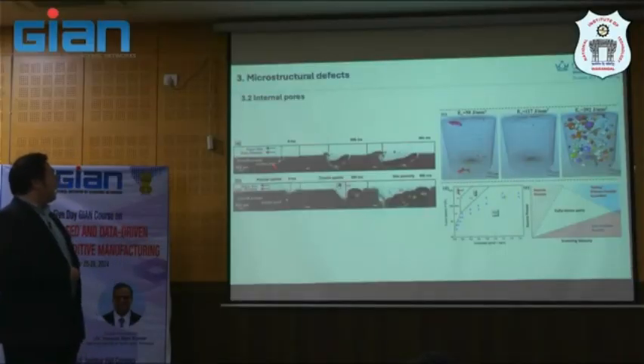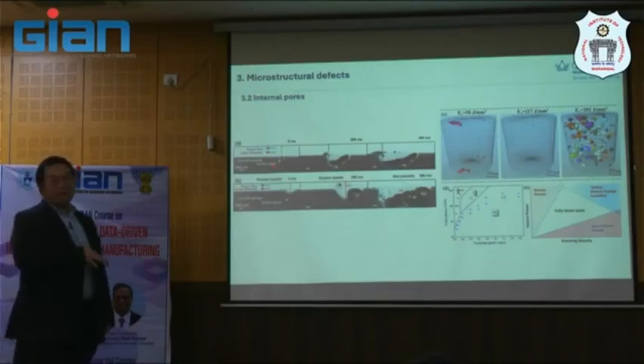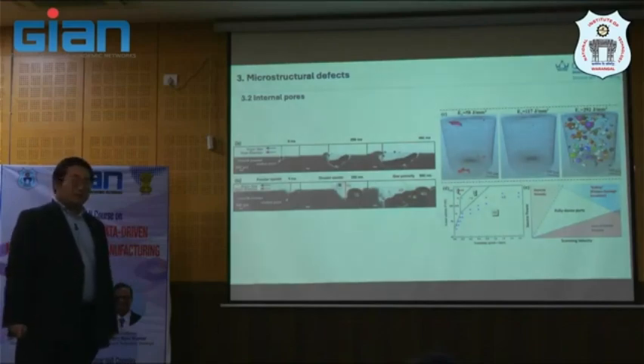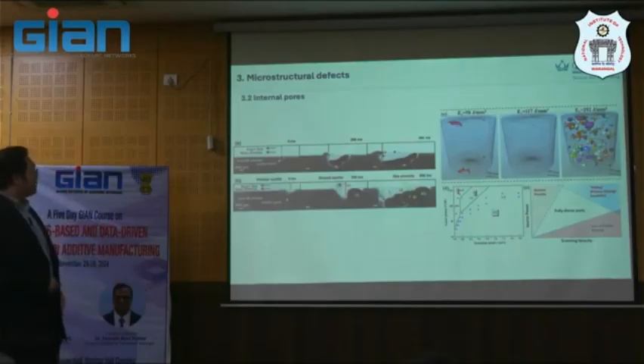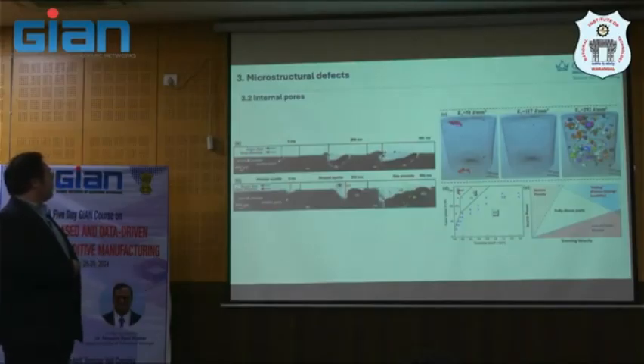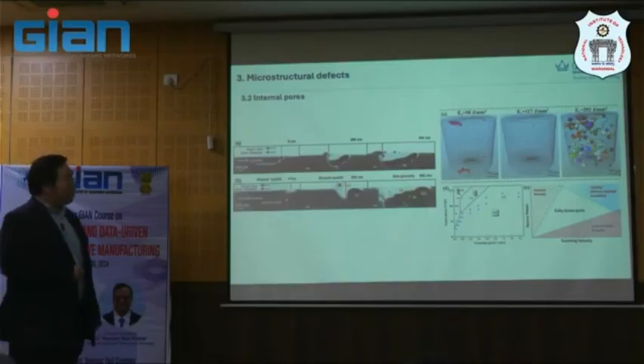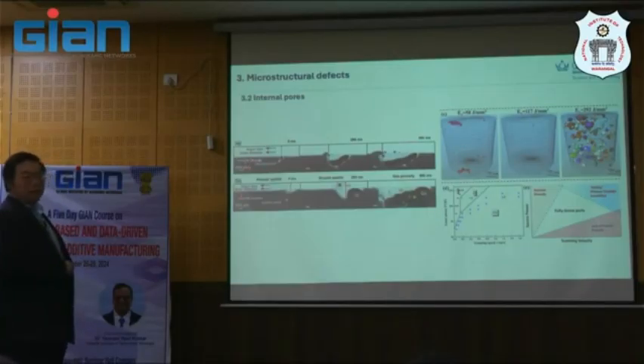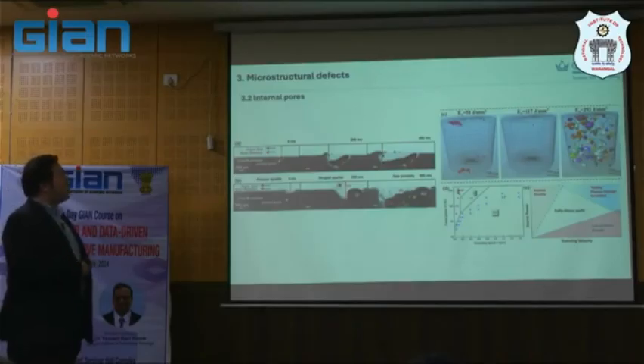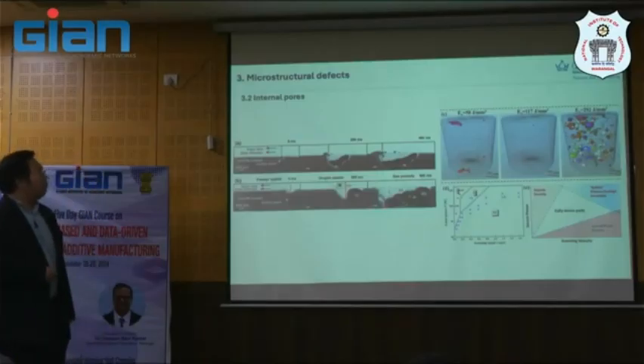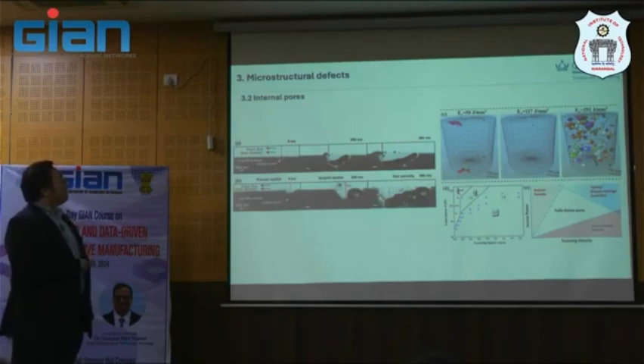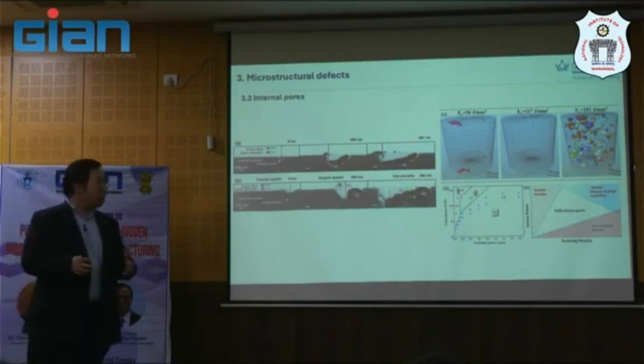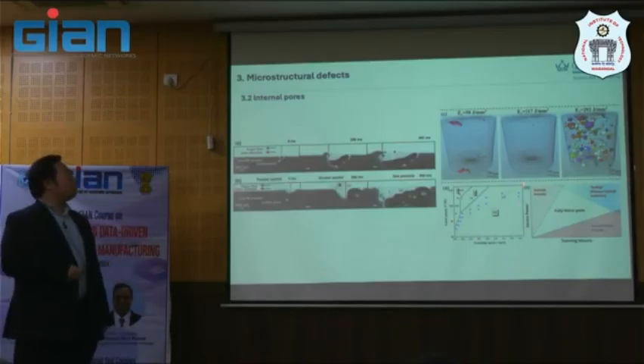laser matter interaction. I think this is basically the first part of today's lecture, just to summarize everything, and then we basically try to predict defect in summary. Actually, this is a porosity in the material Invar, which is an iron nickel alloy. You will see this one for aerospace application here. You see the way they melt leads to the droplet splatter and induces some porosity inside, from this synchrotron imaging here.